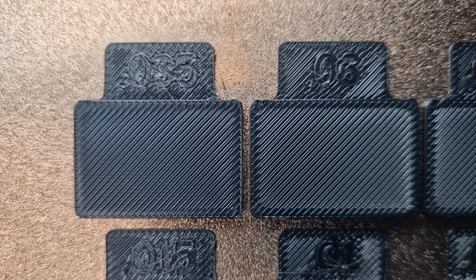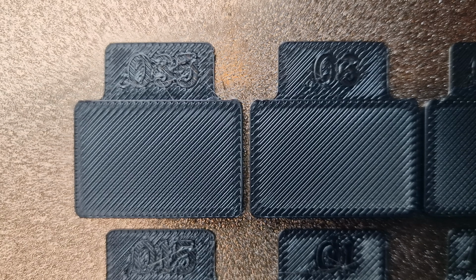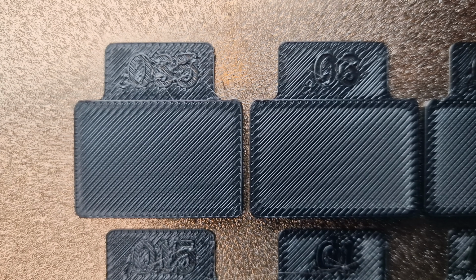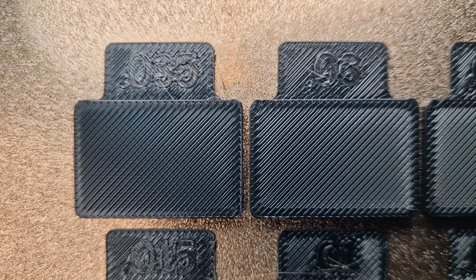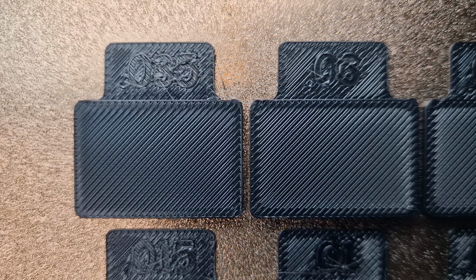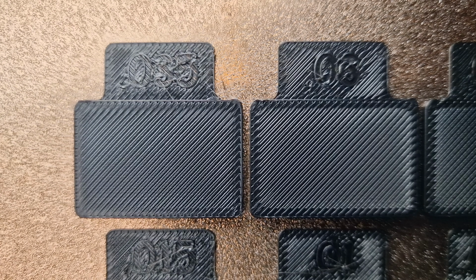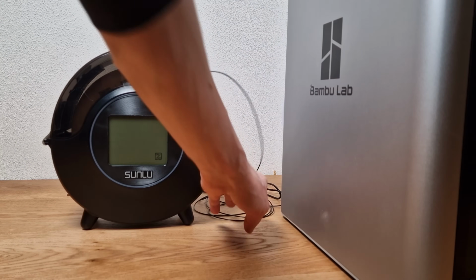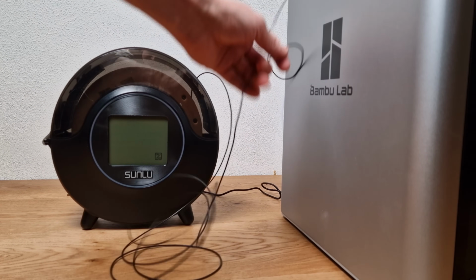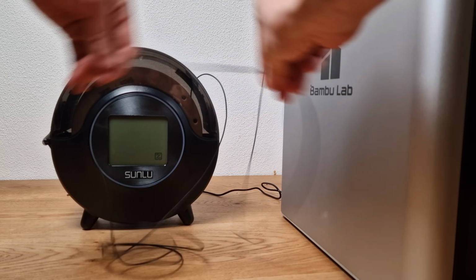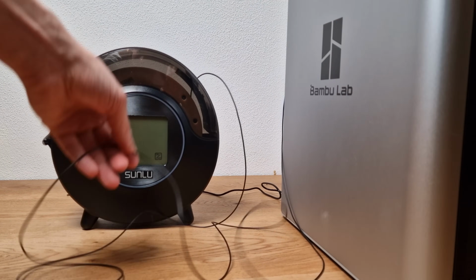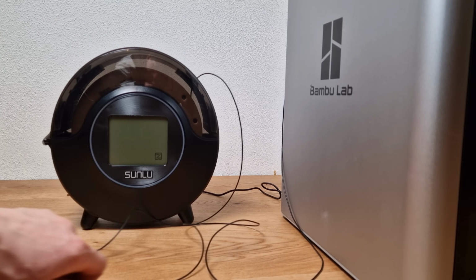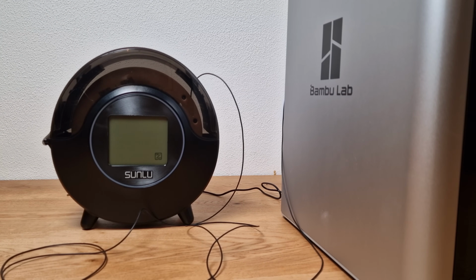If you are wondering how to identify under extrusion, look at the top layer. If you can see gaps between the lines revealing the layer below, that's under extrusion. The top layer should be a smooth, solid surface. To rule out filament feed issues, because remember we have not unwound the filament and maybe there is too much tension and therefore we end up with under extrusion, I manually unwound a few meters and repeated the test.